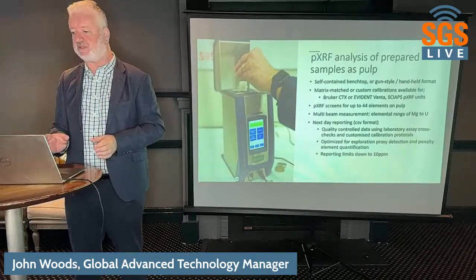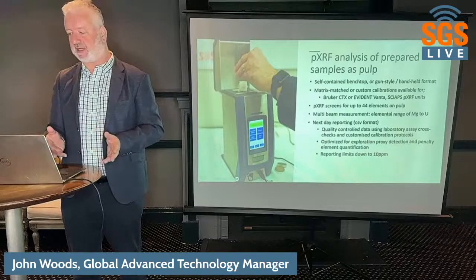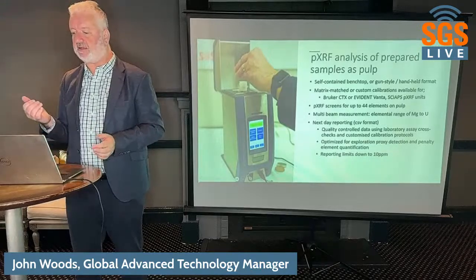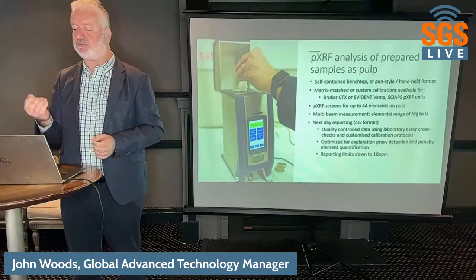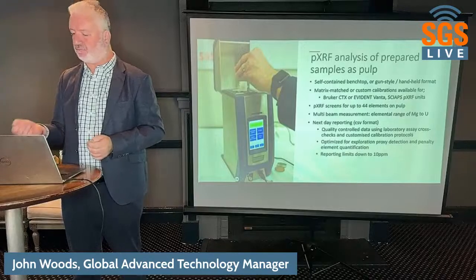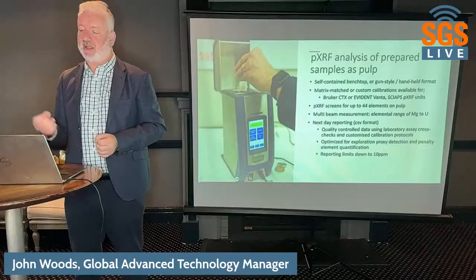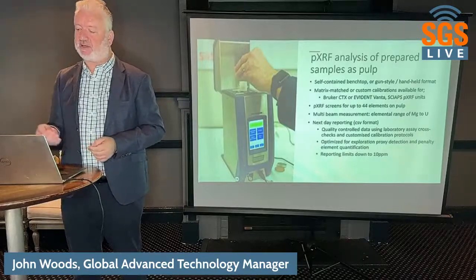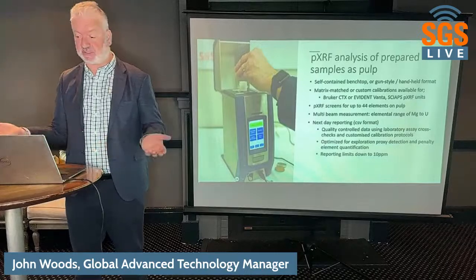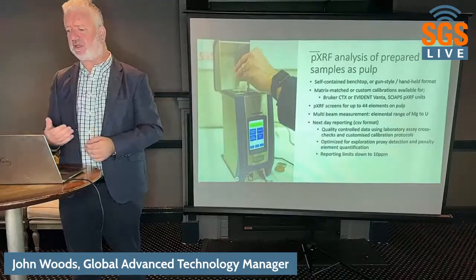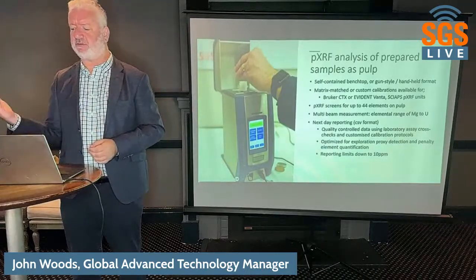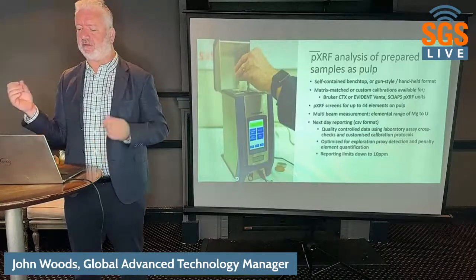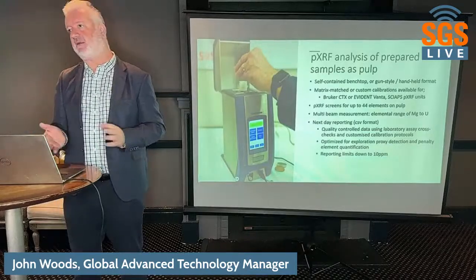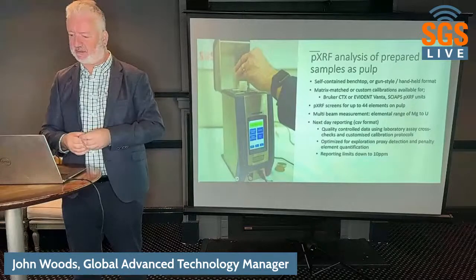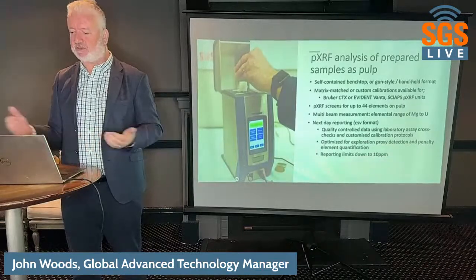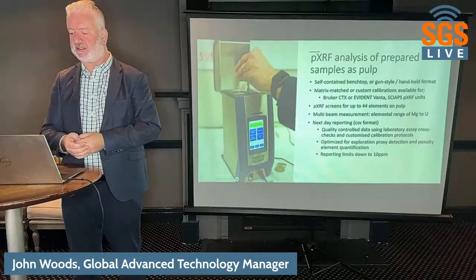The PXRF, they come in a few different forms. We have the self-contained benchtop or gun style. You do need to matrix match those if you want to get reasonable elemental contents, and they can screen for up to 44 different elements on a pulp, usually from the range of magnesium to uranium. If you're looking at a benchtop instrument, that can go as far up as sodium. And we report data routinely in CSV format.